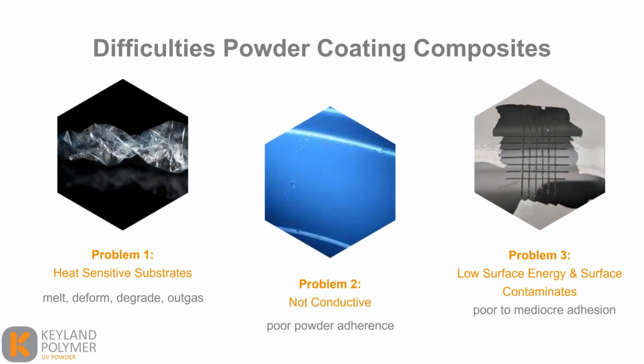Now, from a coatings perspective, these materials provide some difficulties to finish. We laid out 3 different problems here, which we will address and solve throughout this presentation. Problem 1 is that they are heat sensitive, meaning that they'll melt, deform, degrade, or outgas when exposed to excessive amounts of heat. Problem 2, they're not conductive, which leads to poor powder adherence or coating adherence onto the material. And then problem 3, they have a low surface energy and surface contaminants from how they're produced, which leads to poor to mediocre adhesion of the coating onto the substrate.